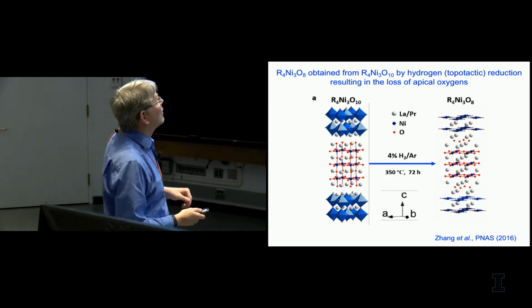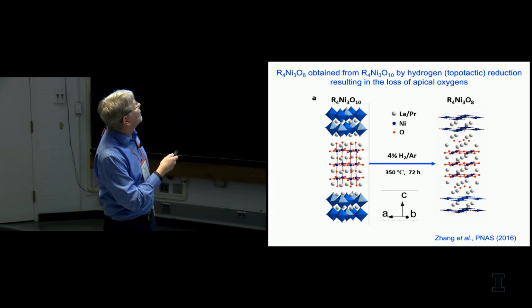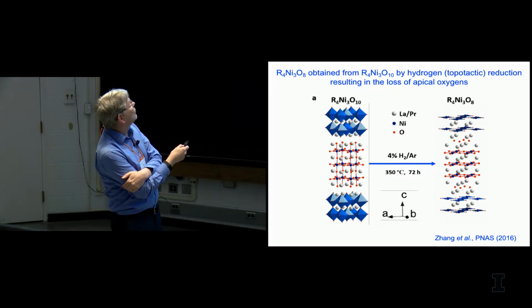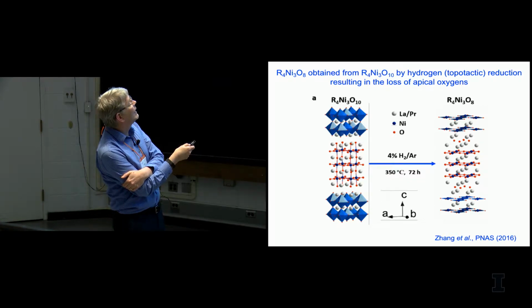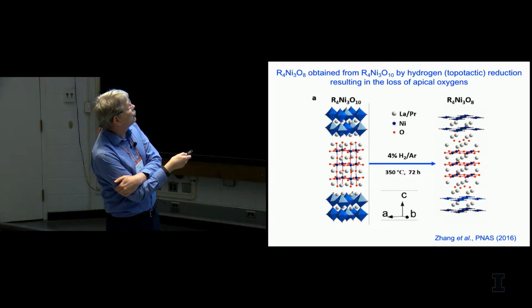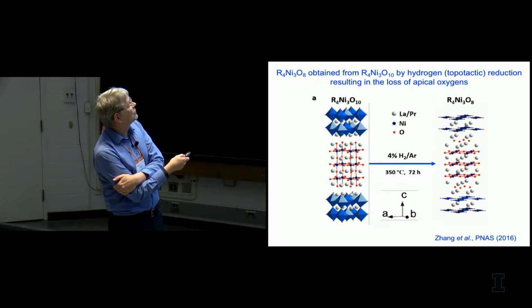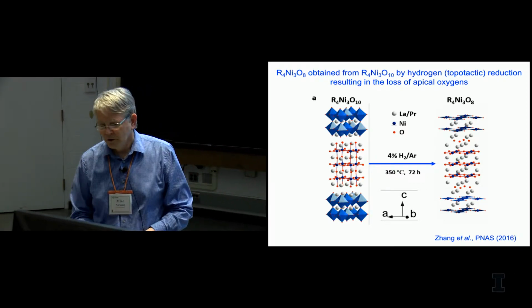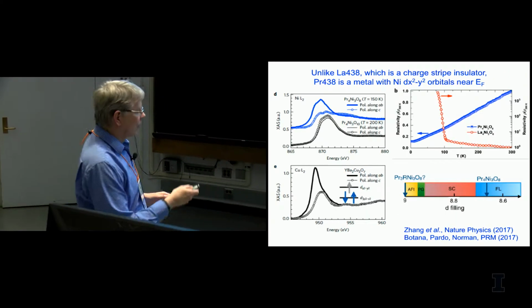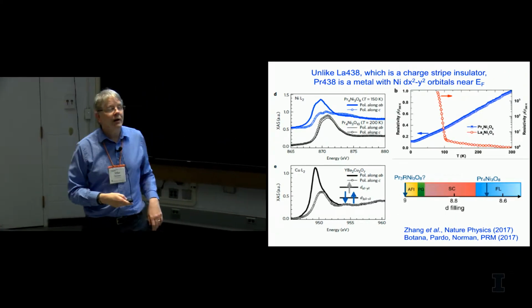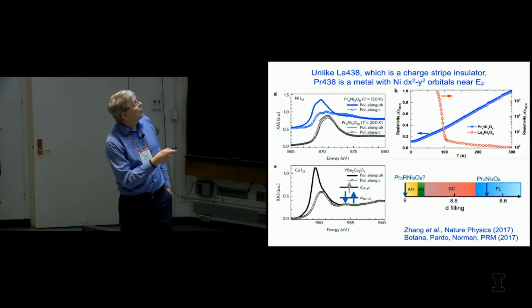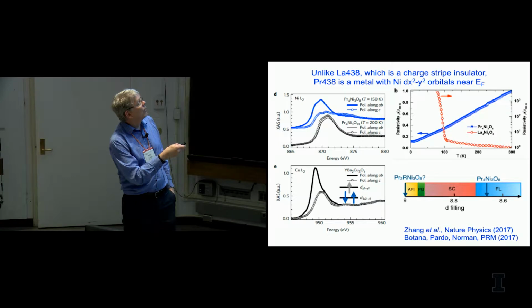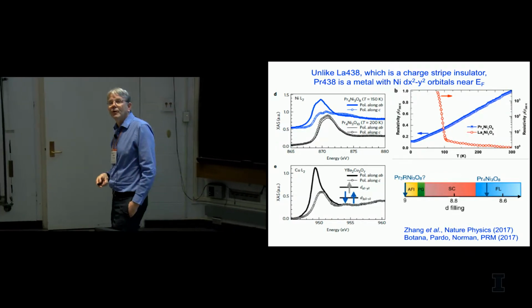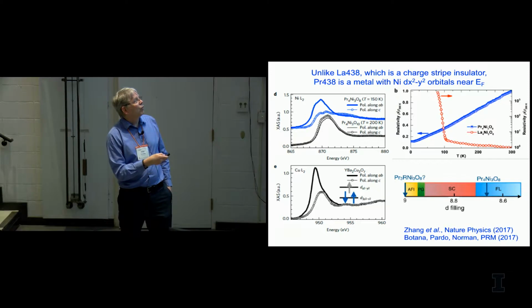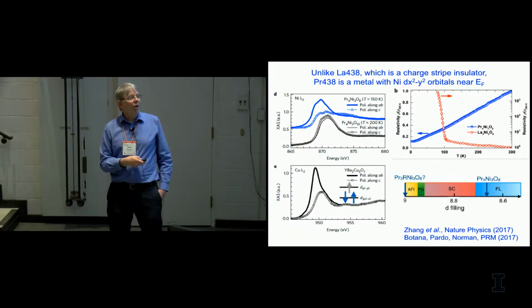And last, there's been a lot of speculation about nickelates. People have tried to make cuprate versions of nickelates, and the most promising thing is to take this 4-3-10 Ruddlesden-Popper phase and do a topotactic reduction to 4-3-8. And this gets you nickel in a square planar environment with a valence comparable to overdoped cuprates. So when people did this with the lanthanum variety, it didn't look very promising. You got a charge-ordered insulator, just like you get in doped lanthanum nickelate. But if you go to the praseodymium version, the thing becomes a metal, and the temperature dependence of the resistance looks remarkably similar to overdoped lanthanum cuprate. So it looks like we found the first nickel analog of a cuprate.